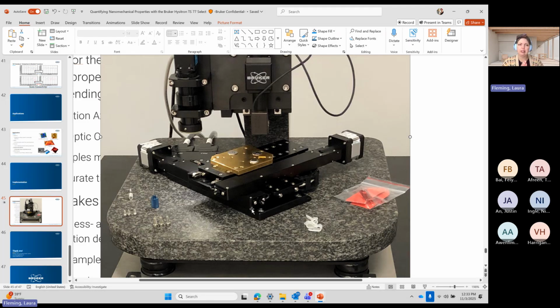There are a couple of key things to do when you install the probe. First, I always recommend you clean it. I don't care if it was cleaned before it was put away. I don't care if it hasn't been used. We're at nano indentation. We should always be cleaning as we go. It's much better to clean now than to get the entire system set up, realize you have a dirty probe, have to take it apart and do it again.